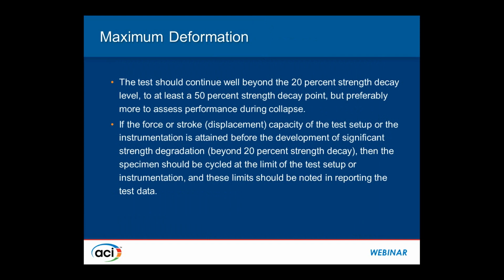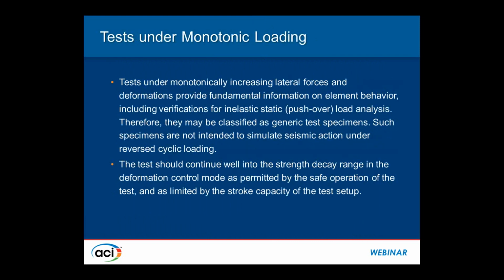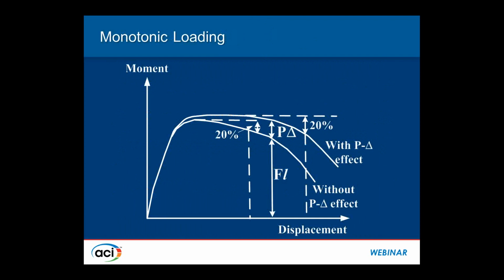Then one may stop at this strength decay point and then keep repeating the cycles until failure occurs. And I'd like to say a few words on tests under monotonic loading, because even though emphasis is on reverse cyclic loading, monotonic load tests provide some very valuable fundamental information. This is analogous to pushover analysis, and it does capture the primary curve. It does give you the initial elastic and post-yield characteristics, as well as strength decay onset. So we do sometimes conduct monotonic tests under incrementally increasing loads.